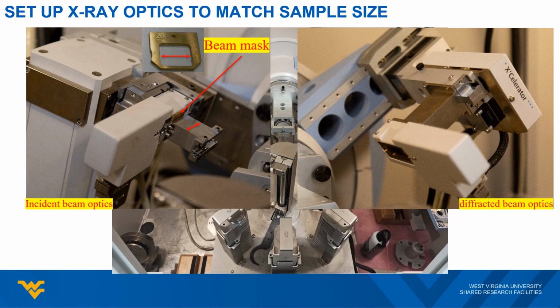We have 4 beam masks with different opening sizes, from the smallest to the largest, labeled as 5, 10, 15, and 20. For standard sample preparation, please use mask number 20, while for the samples using the glass slide and Play-Doh method, please use mask number 15 to get the best result.